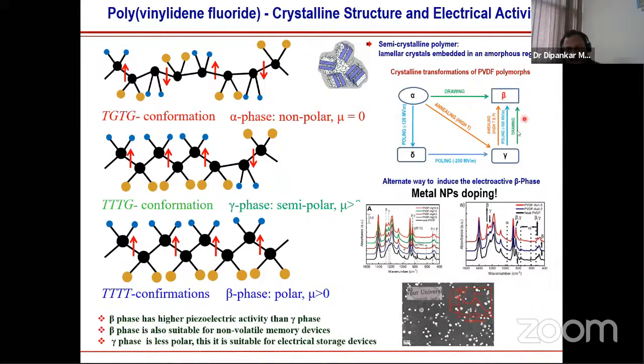And how can we characterize the beta and gamma phase? One simple way is FTIR spectroscopy. This is the new method that we developed: if we incorporate metal nanoparticles in the PVDF matrix, then we are able to induce the piezoelectric phase. So you see in the black spectra, there is no peak at 1275 centimeter inverse, but once we put the silver nanoparticle, you can see this peak is rising up, meaning that this piezoelectric phase is getting formed.